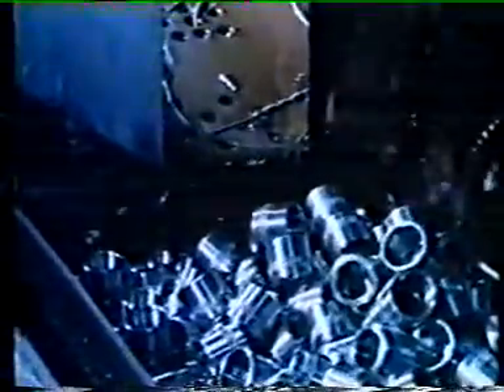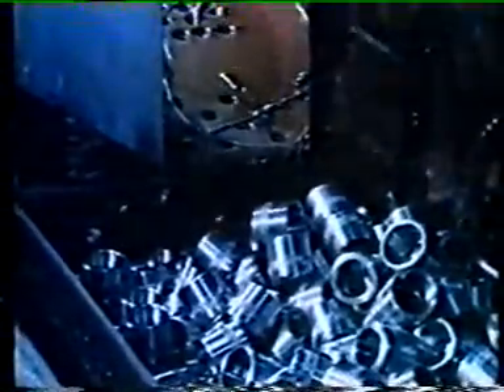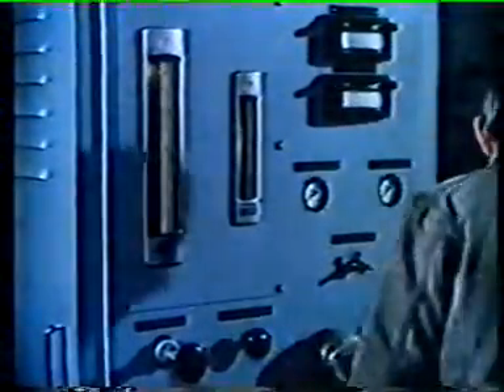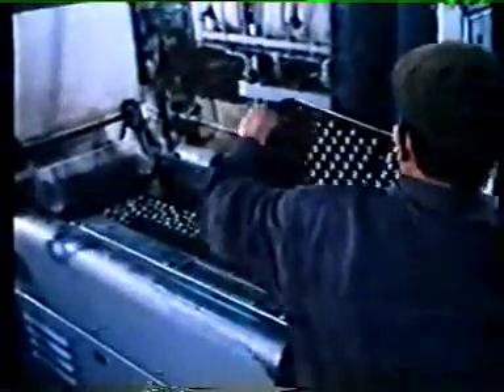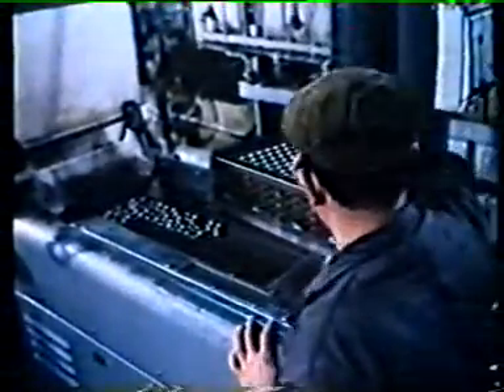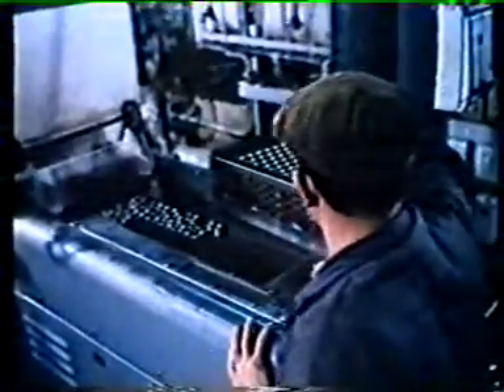These are drill chuck sleeves, and the steel must be hardened in spite of its low carbon content. Here is how it's done. Propane gas is cracked and then fed into a furnace with ammonia gas. The components, placed on a shaking hearth conveyor, are fed into the furnace with its controlled atmosphere. Carbon from the propane and nitrogen from the ammonia are absorbed into the surface of the steel, thus raising the carbon content and introducing nitrogen at the surface only.